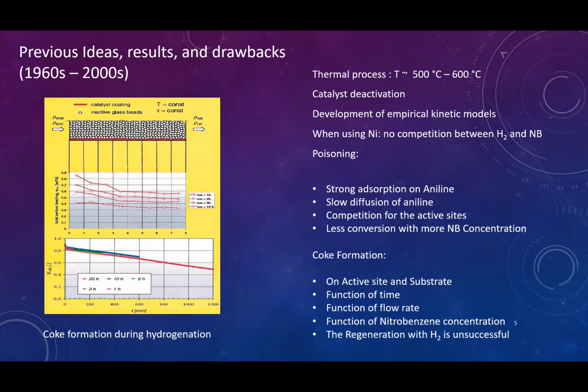Also, we can see that there's a lot of coke formation on the active sites. On the left-hand side, the lower image is the coke formation as a function of time. We can see that there's a linear relationship between the coke and the time. That means that the coke is non-selective. We have coke on the active sites and the substrate. The coke formation was also a function of the flow rate and of the nitrobenzene concentration. The most used process for regeneration of the catalyst was using hydrogen at high temperatures, but this process was really unsuccessful, reaching only about 30% of the initial activity.